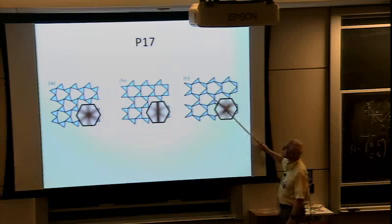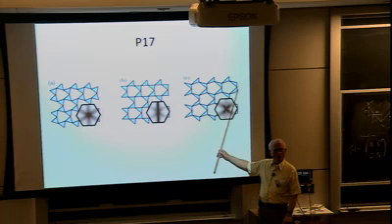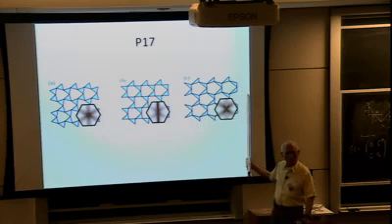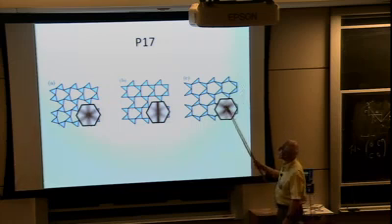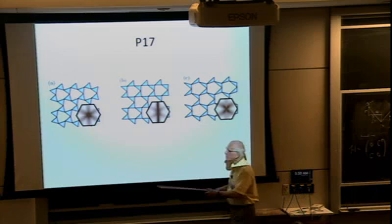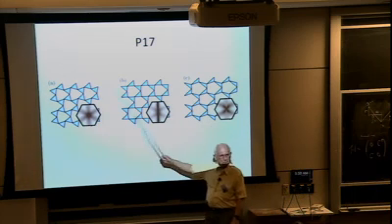It turns out that these are not zero modes. They're modes where the frequency goes as omega squared instead of omega, where omega goes as q squared instead of q. And that form is a consequence of the fact that over on this side, all of these have gapped modes because we're gapped completely.